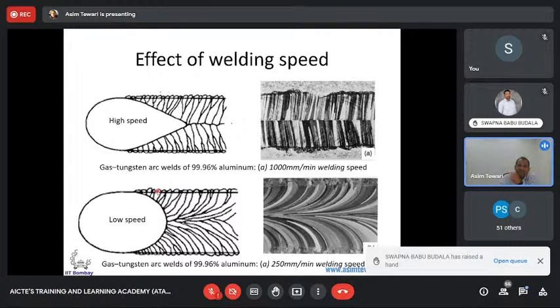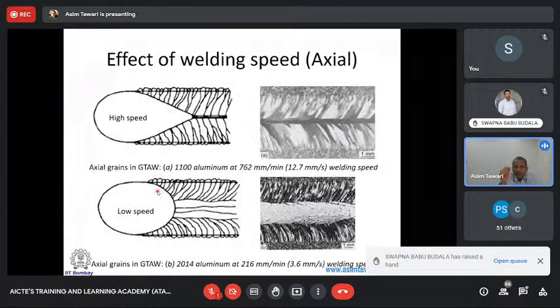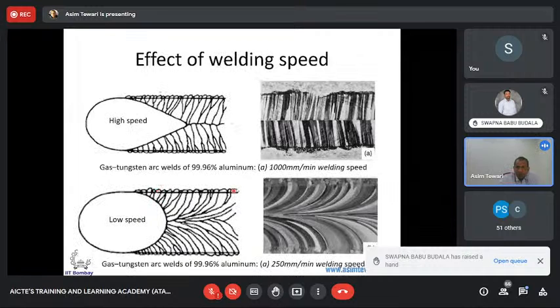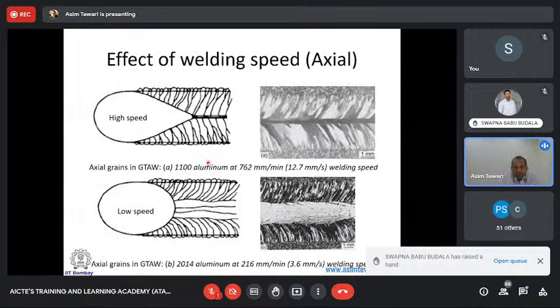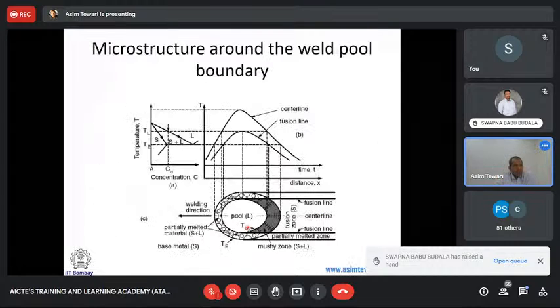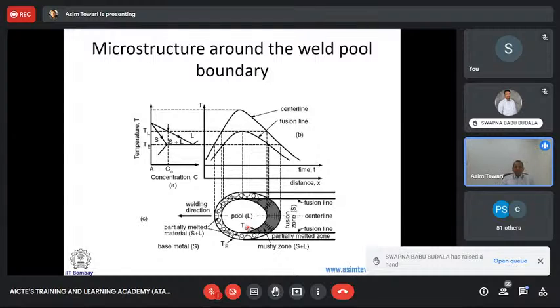So when you go from a single element to an alloy, the previous one was almost pure aluminum. Now when you go to an alloy, that alloy will lead to a slightly distorted, a different kind of microstructure. So the same process window for a pure metal versus an alloy versus another alloy, depending upon the range of solidification, you could create very different structures. And within the pool of liquid metal itself, there will be temperature variations which will occur.